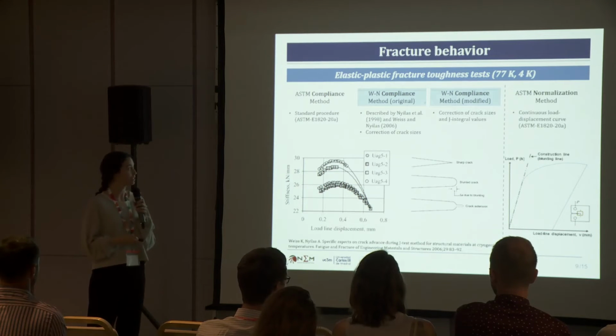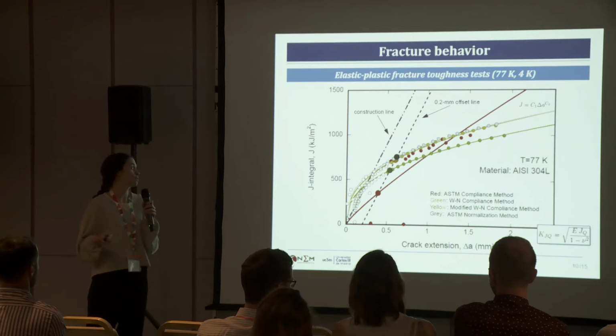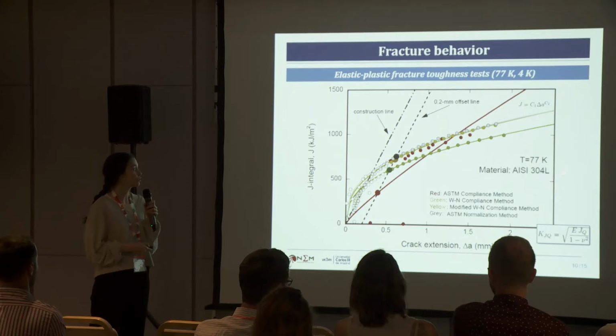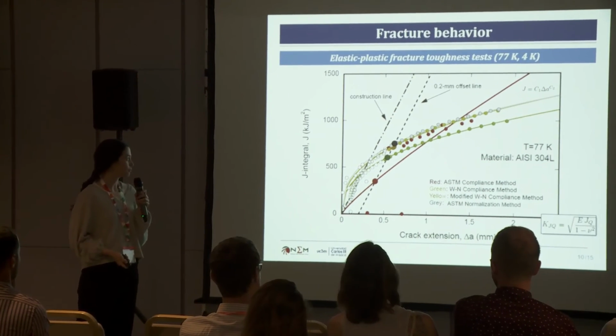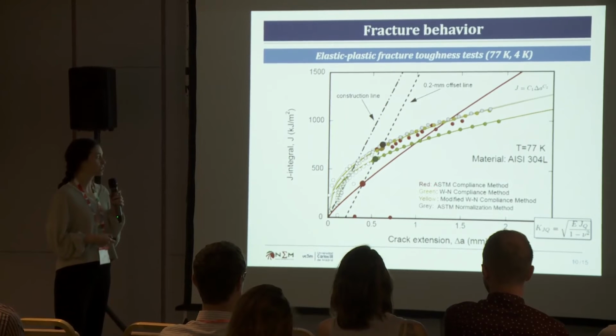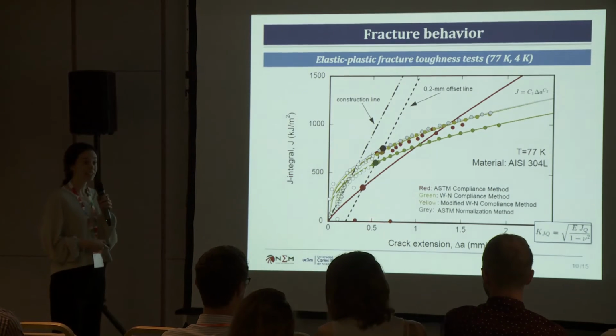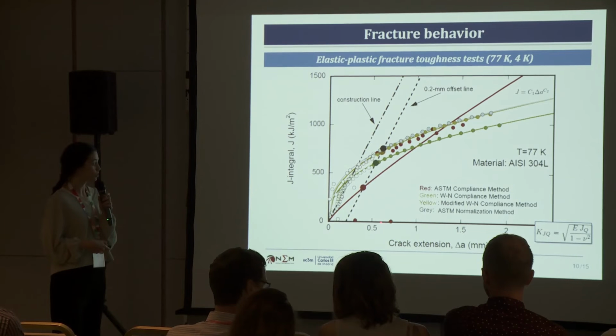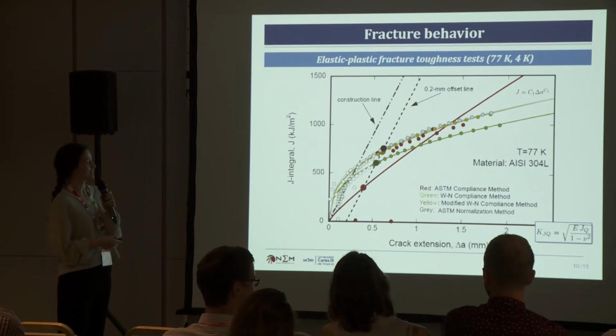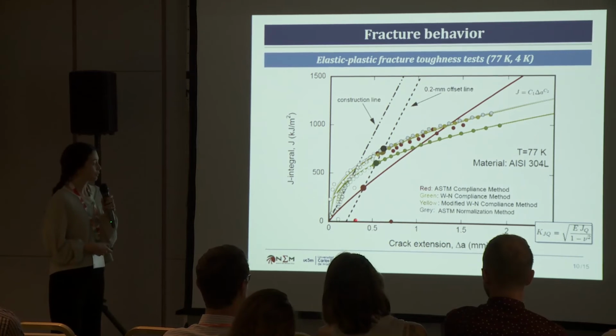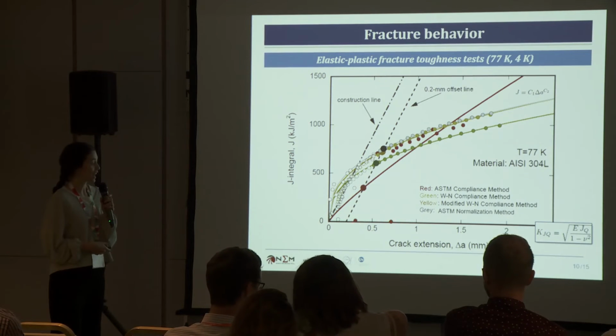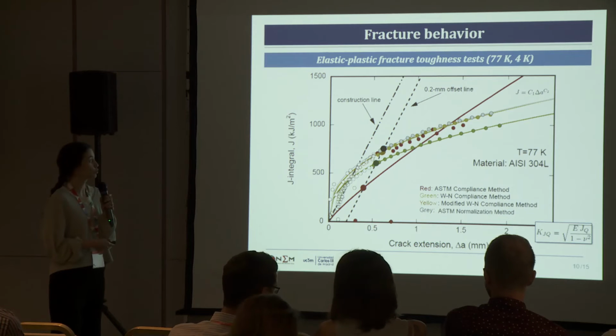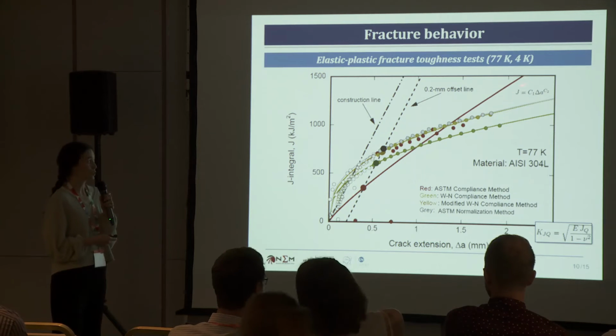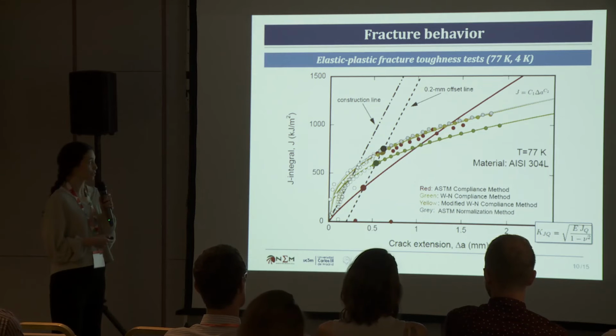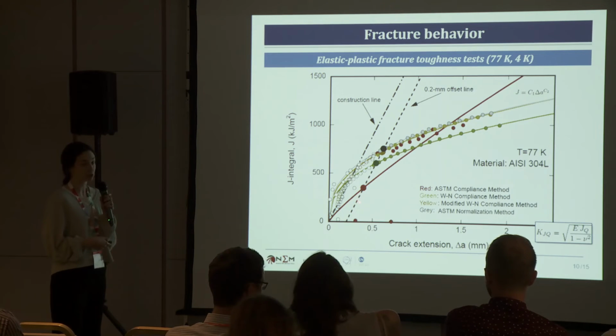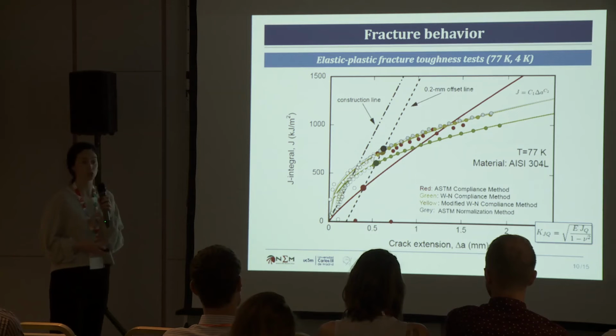Let's now compare them for one fracture toughness test that we did for the AISI 304L at 77 Kelvin. So we have the ASTM compliance method in red. We see here the negative crack extension. You see, the points go to that side and then it increases. The problem here is that we have 2 points in the qualified area. So according to the standard, we have to use those 2 points to calculate the regression power law line, which, as you see now, is not representative of the rest of the points. And then you have here the J_Q, that of course is not representative either. So this method is not suitable for us.